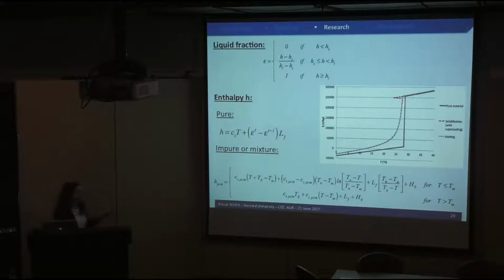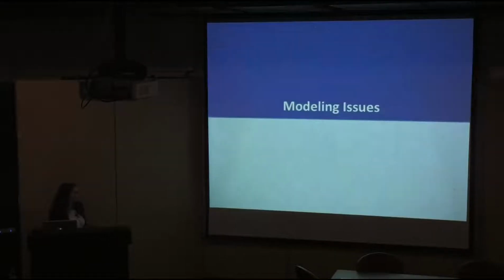unless we dip past this nucleation condition. This condition applies just in the solidification part. In the melting part, the material follows the gray curve, but in the solidification part it follows this one according to a certain degree of supercooling. And this was obtained inversely. We will see how we obtained it inversely. And this is how the enthalpy-temperature curve will look when we add the impurities, the factor of having soluble impurities, other than this one for the piecewise function.